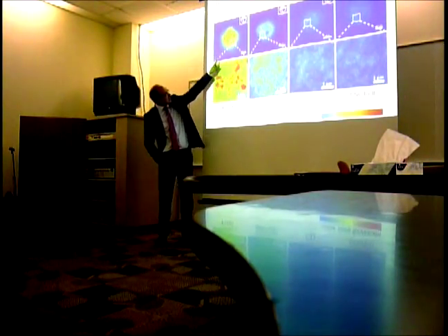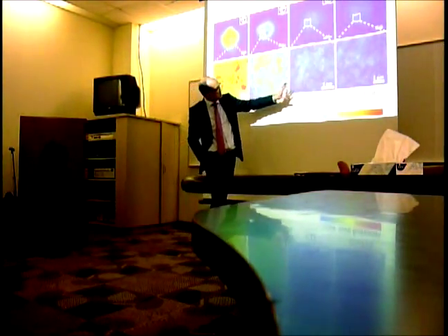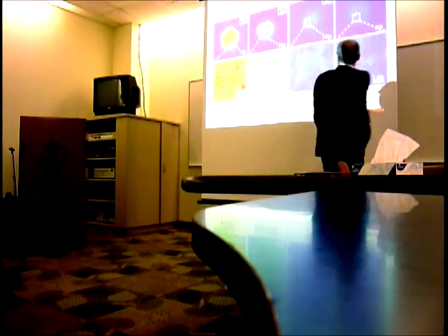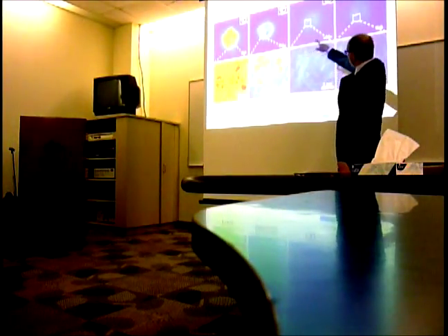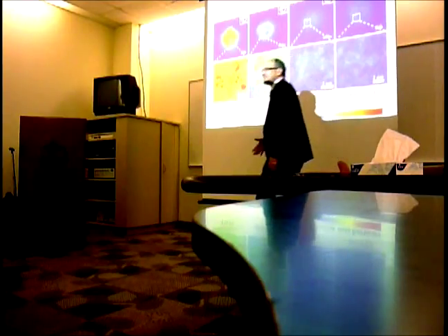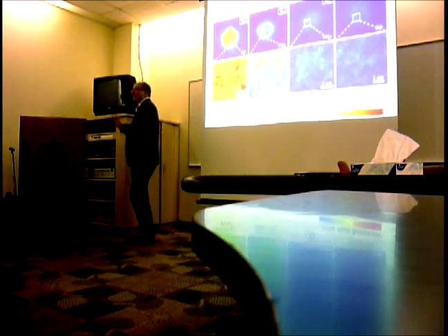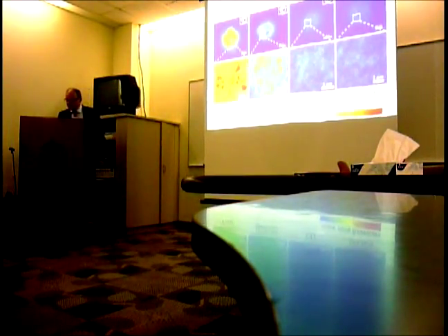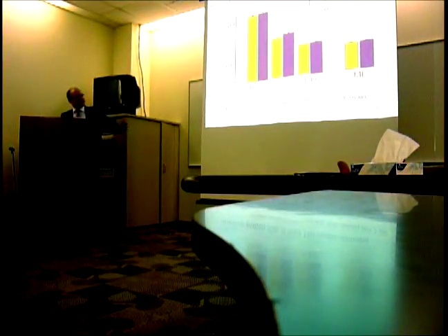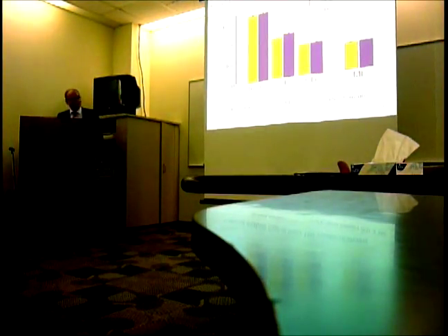Because then we should see a decreasing contribution of our zeolite. And it is indeed the case. This is the fresh, steamed, coked and metal deactivated. So here you see how the color is fading away as the deactivation proceeds. You can do statistics on this, and then you have numbers.